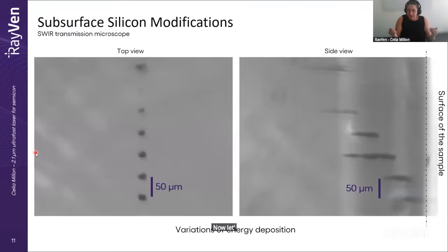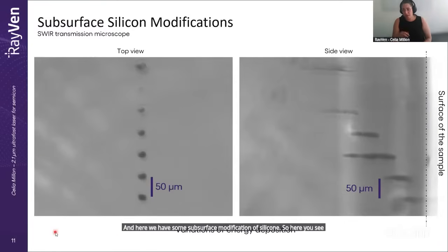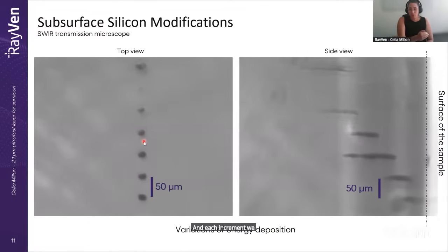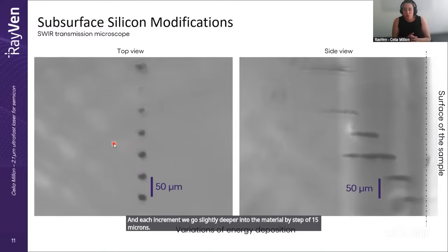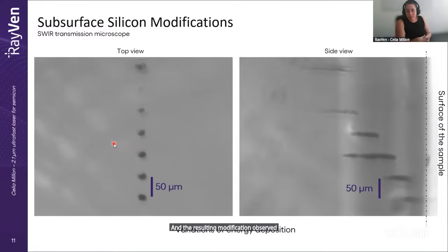Now let's go inside the sample. Here we have some subsurface modification of silicon. Here you see a laser source operating at 40 kilohertz, and at each increment, we go slightly deeper into the material by steps of 15 microns. The resulting modification observed went from the surface to roughly 200 micrometers, with lengths between 50 to 100 micrometers.